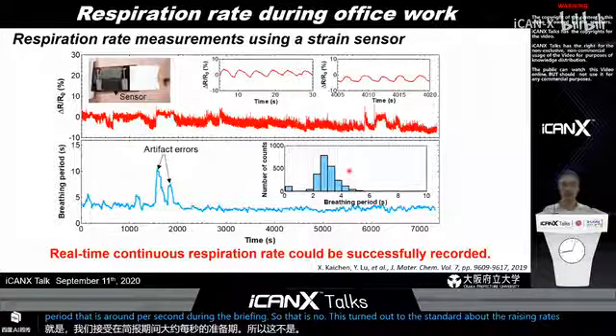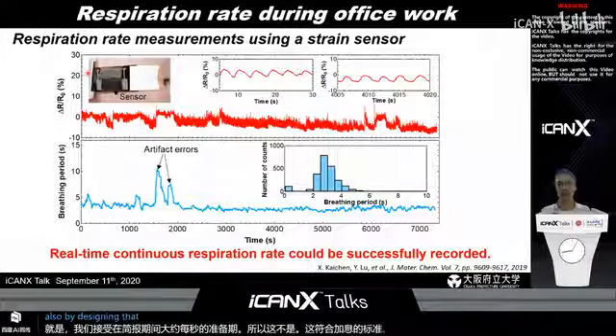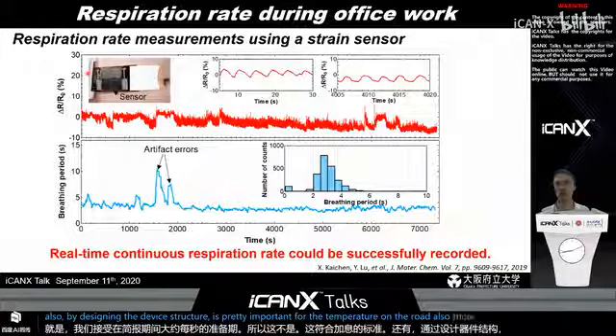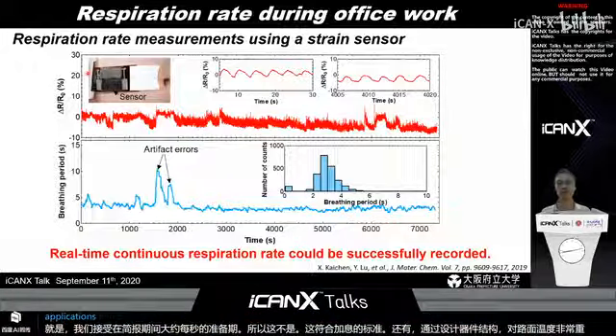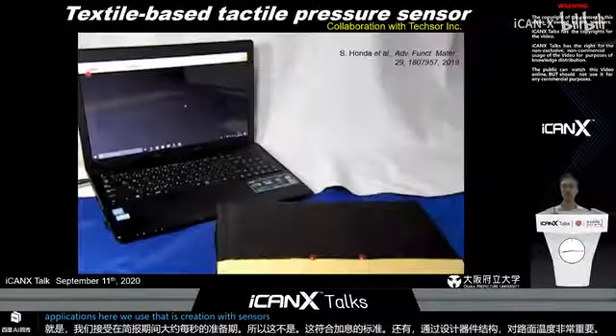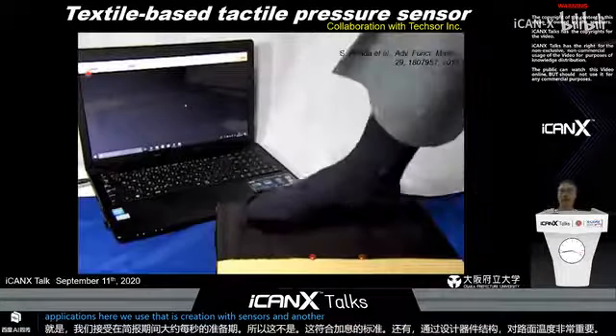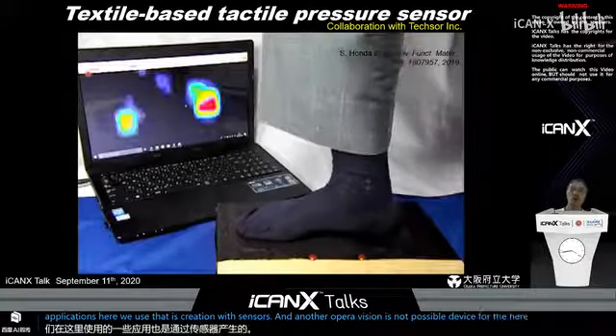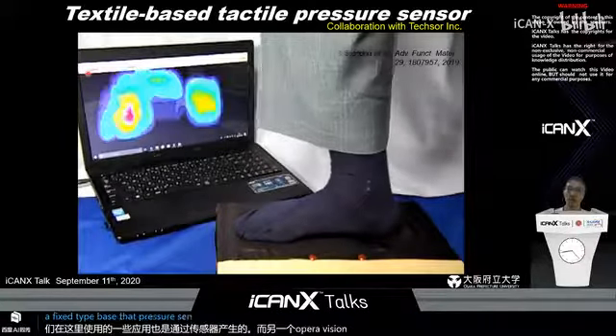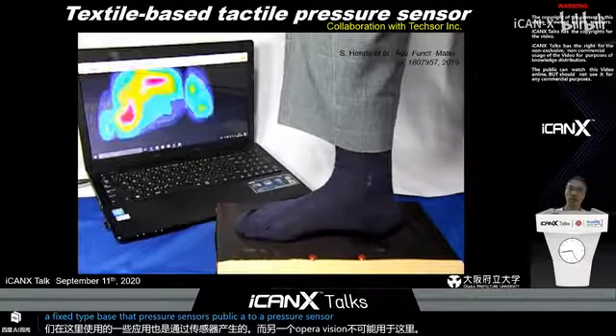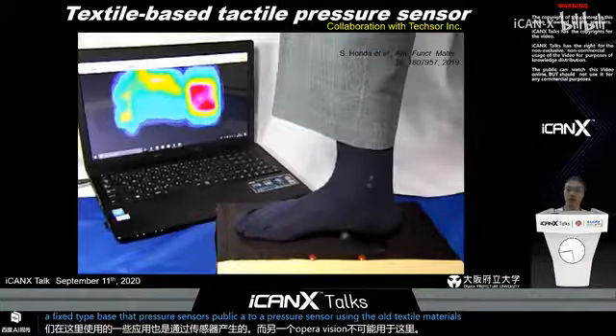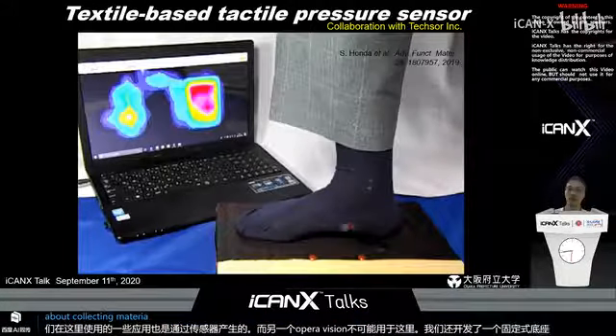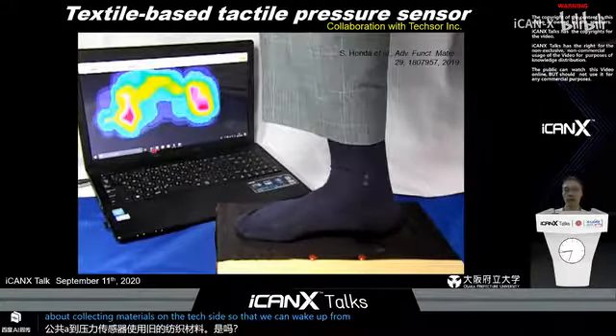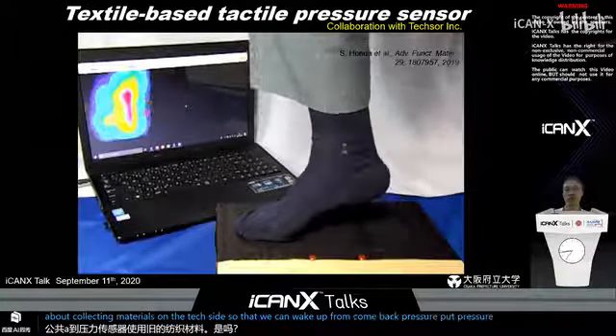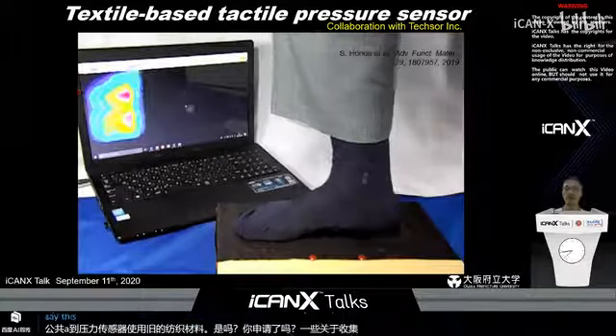So designing the device structure is pretty important for temperature and also some of the stretchable applications. Here we use the respiration rate sensors. Another application is a touchable device: here we also developed textile-based tactile pressure sensors. We fabricate a pressure sensor using old textile materials, and then we apply some conductive material on the textile so that we can monitor tactile pressure, foot pressure distribution, and you can see this in the movies.